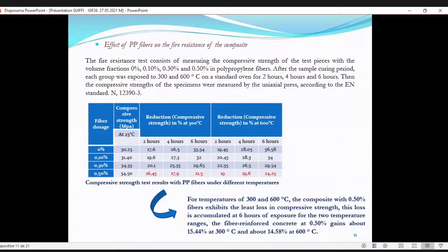In this study, we used the tensile strength and compressive strength and other measures for the results. But in this research, we are focused on the compressive strength, and for 0%, 0.10%, 0.30% and 0.50% of polypropylene. And we can see in the table the degrees of the reduction in percentage between different temperatures.